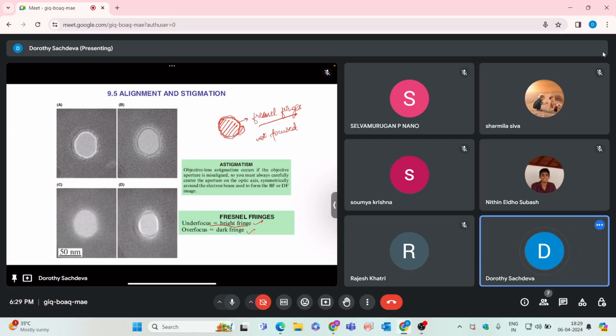Astigmatism of the objective lens, if it is completely corrected, then you will have this circular beam on your fluorescent screen, and if you converge and diverge it, that means increase or decrease the intensity, then it will uniformly go in all directions. But if it is astigmatic, then it will go like this, and the other way it will go like this, once here and once here. But it should go uniformly in all the directions. So if it is going uniformly, then we can say that astigmatism is being corrected.